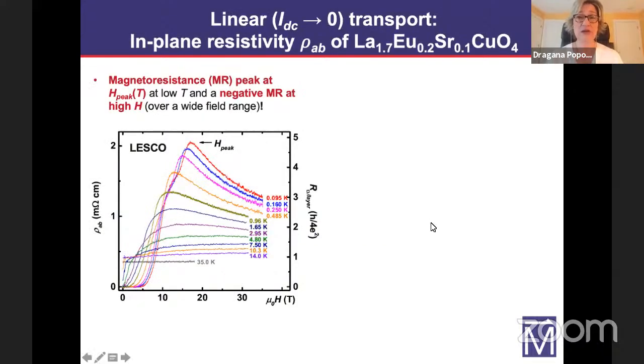So first I will start with linear transport, and I can only, of course, show you a fraction of our measurement results. So I will focus on LESCO here. We are focusing first on the in-plane resistivity in the limit of zero current. Here is the dependence of the in-plane resistivity on the perpendicular magnetic field at different temperatures. At high temperatures, there is essentially no dependence on the field, or it's very weak, because we are in the normal state. As we reduce the temperature, one starts seeing positive magnetoresistance, which is well understood to result from the suppression of superconducting fluctuations. And as we reduce the temperature further, we start seeing a peak in the magnetoresistance, which becomes very sharp at very low temperatures, followed by this wide region of negative magnetoresistance.